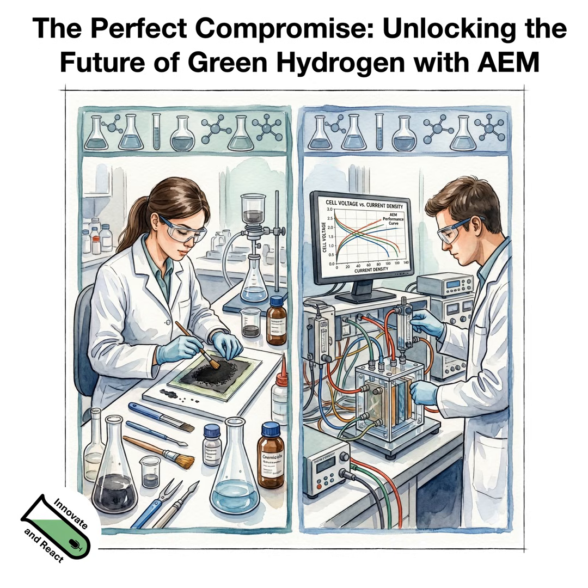So as previously mentioned, we measure the current or the voltage between anode and cathode. But to see only the anode, you would need another reference point, or so-called reference electrodes, as is common practice in lab-based work. But that's not too easy to do on a real cell system, and we are also looking into reintroducing a reference point so that we can measure only the anode losses and only the cathode losses, because then we can be more certain that our new material actually degraded or did not degrade.